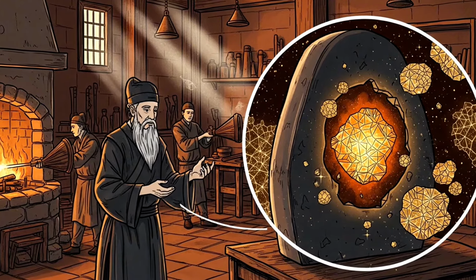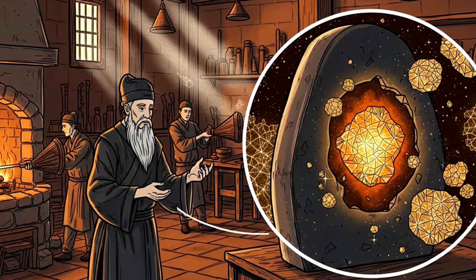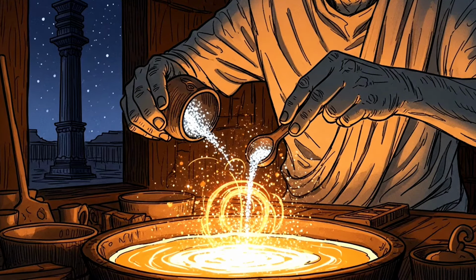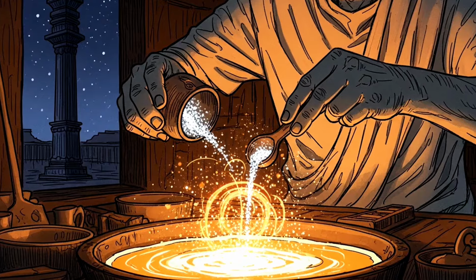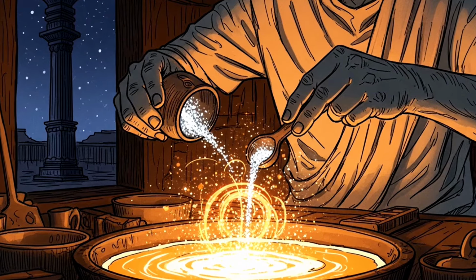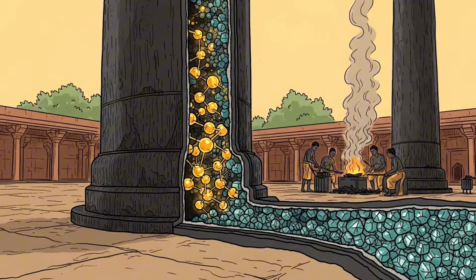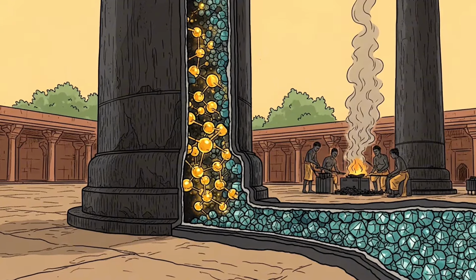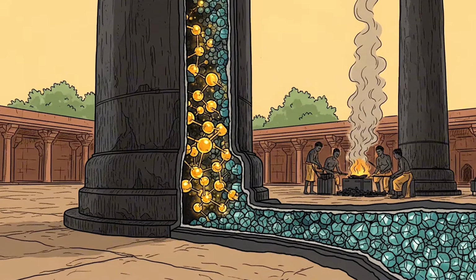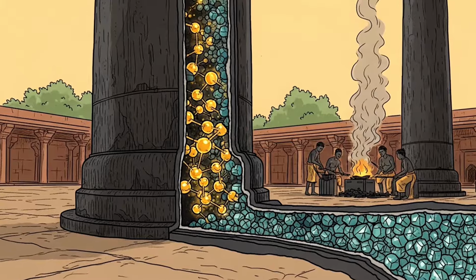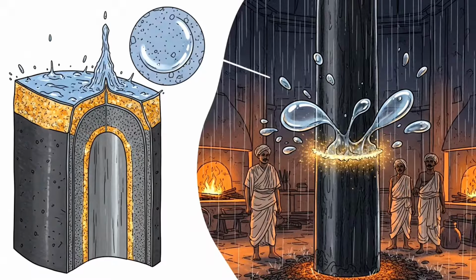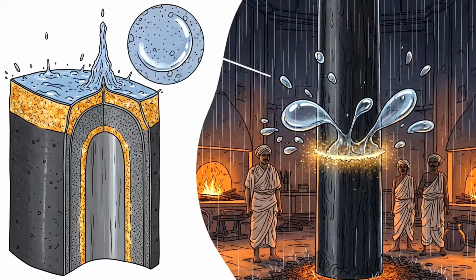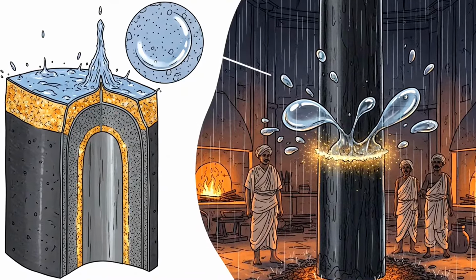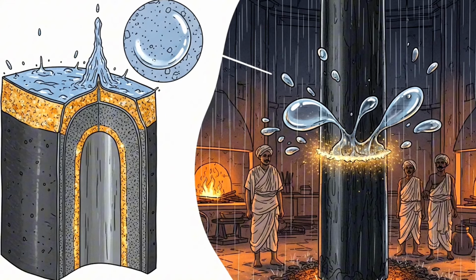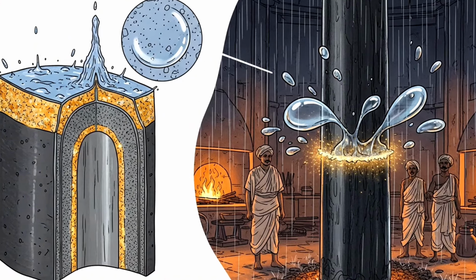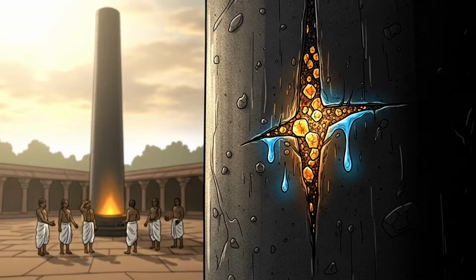But the chemical key lies in something unusual about this particular iron. It contains an abnormally high phosphorus content, a substance modern steelmaking deliberately removes because it makes steel brittle. In the pillar, that phosphorus does something remarkable. It catalyzes the formation of a dense, stable protective film called misawite, which is iron hydrogen phosphate hydrate. This misawite layer is only about 1/20th of a millimeter thick, but it is completely impermeable, sealing the iron core from oxygen and moisture. And it is self-healing.